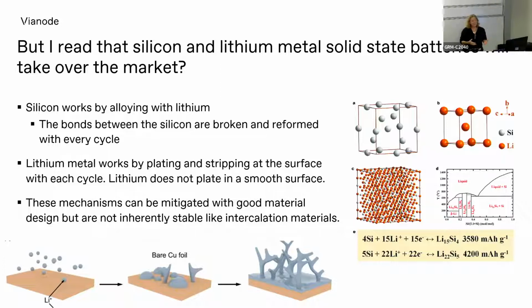But what we see is that when people talk about how silicon is the new anode material, how silicon has greater energy density, how silicon is going to take over the anode material market, what they forget about is that the way that silicon works is fundamentally different from the way that graphite works, where silicon is an alloying anode material. So if you look at the picture up on the right, you can see the structure that you get for the atoms in crystalline silicon. And then if you look just below that, you can see the structure that you have when you have fully lithiated silicon material. And you'll notice that all of those little orange balls, those are the lithium. And that's because you have, for every one silicon, more than 3 lithium atoms.